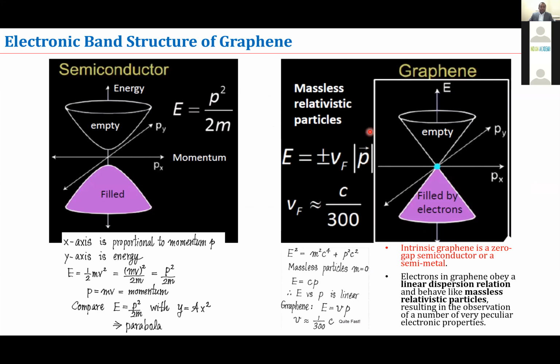And then if we compare graphene with a semiconductor, for a normal semiconductor, we know that you can use a Schrödinger equation to describe the electron motion in a semiconductor. The energy and momentum are described by E = p^2/2m, which is a parabolic equation, and therefore you can expect a band structure of this nature, where you have a filled valence band and an empty conduction band, and you have a band gap. However, in case of graphene, the energy and momentum are linearly proportional because the electron can move very fast and it is massless. So the velocity of the electron is almost equivalent to the velocity of light divided by 300.